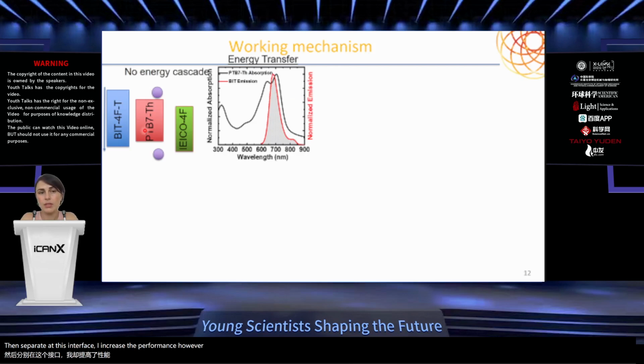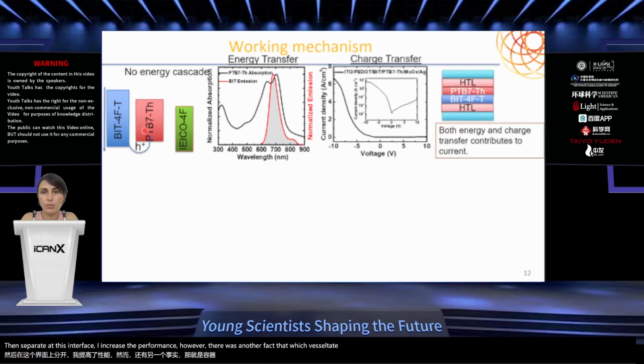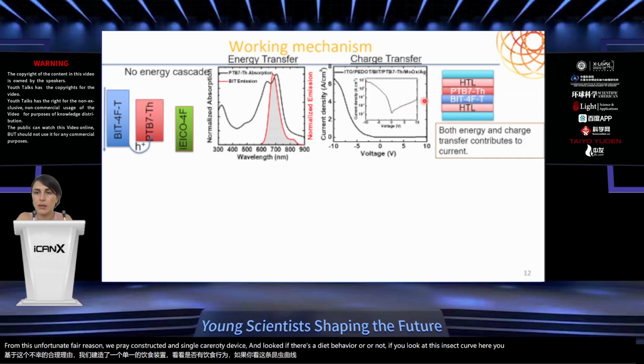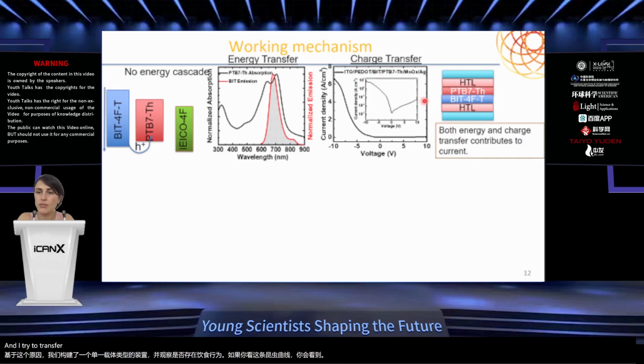However, there was another factor which facilitates further performance, which is a hole transfer, if a hole transfer would occur from this. For this reason, we constructed a single carrier type device and looked at whether there's a diode behavior or not. If you look at this inset curve here, you see that a charge transfer was contributing from the BIT4F-T to the PTB7-Th molecule layer in this case.